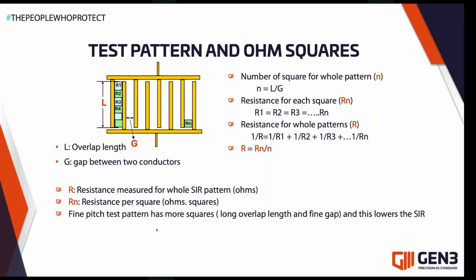So when we look at our SIR pattern, we like to think about how many squares can I make up sitting between each electrode in all of those interdigitated comb parts, so we can count those up. It turns out that the resistance of the pattern is simply the resistance of the square divided by the number of squares. So we get a geometric amplification, and hence we can measure lower resistance than actually the resistance of that square, and that helps us with the equipment, because otherwise we'd be measuring much higher resistances.